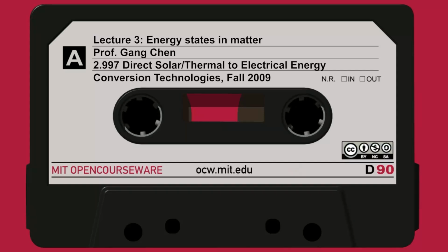But in the solid, when you look at the transport, I treat that as a free electron. Then due to the field, the drag of the background lattice, now they feel either heavier or lighter than the free electron mass, which is 9.1 times 10 to the minus 31 kilograms.